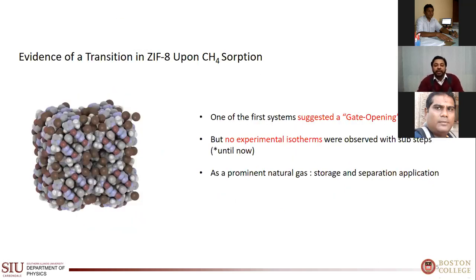Again, this is more related to the natural gas industry. We've looked into the methane and ZIF-8 interactions, and surprisingly, methane also introduces a real change in the structure. It expands the structure, and ZIF-8 absorbs more methane. So this shows us that ZIF-8 has so many applications, starting from capturing toxic gases like carbon monoxide and carbon dioxide, of course, and also absorbing radioactive or rather inert gases like xenon in a different environment.